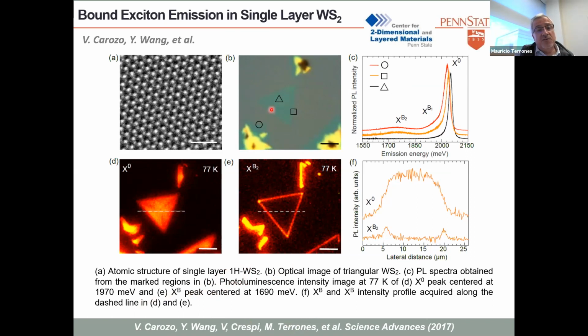And so this is again tungsten sulfide. You have the monolayer. And this is the photoluminescence, right, of the neutral exciton. That's the one that I showed you in my first slide when you have the direct band gap. So this neutral exciton is the X0, and this is at 77 Kelvin. So one thing we noted is that the neutral exciton, if you map the neutral exciton, it's all this triangle. But there's a second peak at this temperature, which we call a bound exciton. And that happens 280 milli-electron volts below the neutral exciton. And this one can be localized on the outside of the triangle.